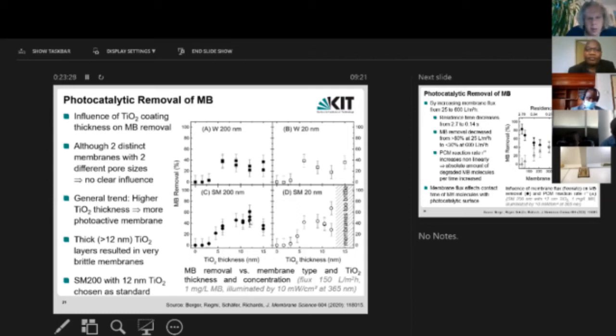Here, you can see that there was a peak performance at about 12 nanometers. I wouldn't trust the values going higher than this, with 15 nanometers therefore being worse. What did happen after 12 nanometers, though, was that the membranes became very brittle and they cracked a lot. So the mechanical handling of these membranes for thicker titanium dioxide coatings was terrible. This was another reason to stop at about 12 nanometers.